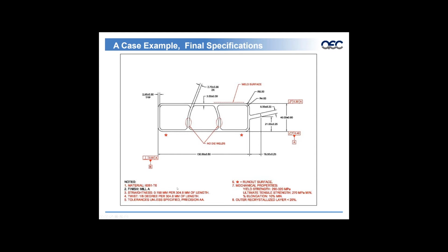Tolerances, unless specified otherwise, were changed to a precision AA. We noted our runout surfaces so that we understand if there are any graphite marks from the runout, they're on a non-welded surface. We specify our mechanical properties with a specific yield strength. So we applied a band, specified the requirements relative to the balance of the mechanical properties, and put a specification on a recrystallized layer. We also noted in this application that no die welds could be applied in this area as a result of the performance need of the extrusion.